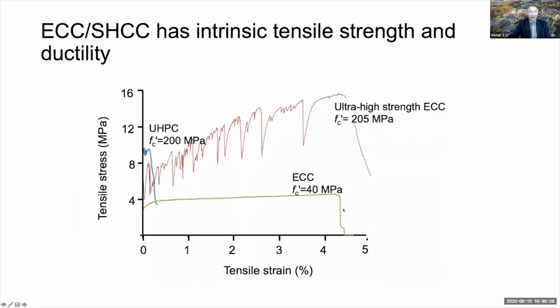The ductility of ECC is best exemplified by the tensile behavior. These curves are obtained by uniaxially tensioning a piece of ECC. And you can see that after the elastic range, it undergoes a pseudo-strain hardening behavior with as much as 4.5% strain. This large tensile strain capacity is roughly about 400 times that of normal concrete.